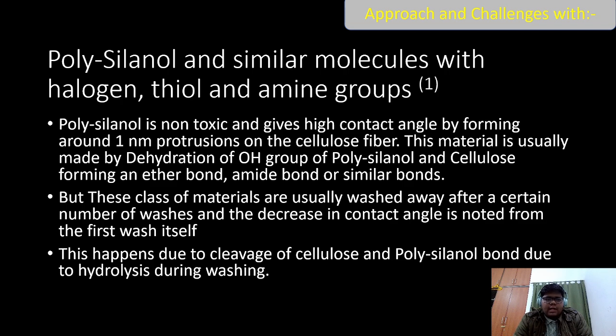Polysilanol and similar molecules with halogen, thiol or amine groups have also been researched. Polysilanol is non-toxic and gives high contact angle by forming around 1 nanometer protrusions on the cellulose fiber. This material is usually made by dehydration of OH groups of polysilanol and cellulose, forming an ether bond, amide bond or similar bonds. But these class of materials are usually washed away after a certain number of washes, and the decrease in contact angle can be noted from the first wash itself. This happens due to the cleavage of cellulose and polysilanol bond due to hydrolysis during washing.